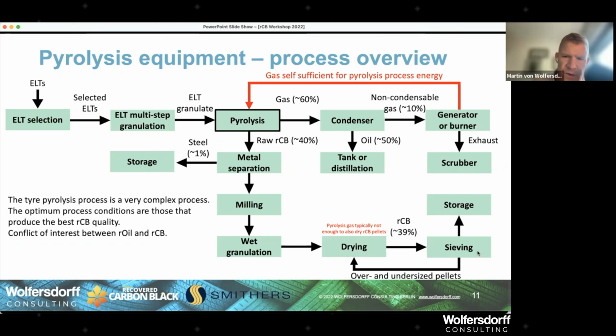And after that, you go into sieving because you want the pellets of a certain size. The smaller pellets and the larger pellets go back to the milling and they're pelleted again so that the output of the pellet size is pretty consistent. And then you would pack, and that typically to start with is big bags or super sacks of between 500 kilograms and up to 1 ton, depending really on the density, because a 1 ton carbon black big bag is like 2 meters high and only works out if the density is high enough, the pour density.